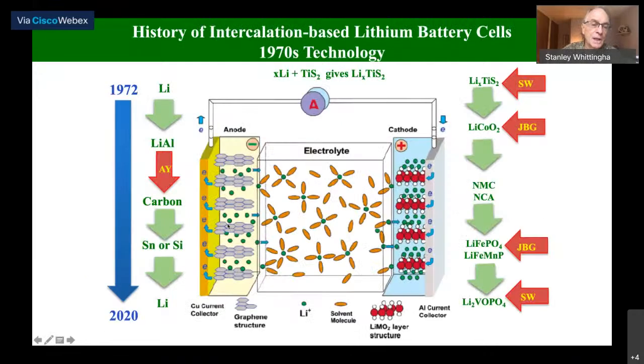So let's just do a little bit of history on the lithium battery. I'll show you a few of the key issues with it. So a lithium battery has an anode, where the lithium is stored on fully charged, a cathode, where the lithium goes, and in between is an electrolyte, and this has to be organic, or it could be a ceramic, because otherwise it would react with the lithium metal. And in between this interface, a protective layer is formed when the battery is first built, which protects the organic from the lithium metal. So in 1972, we used lithium metal.